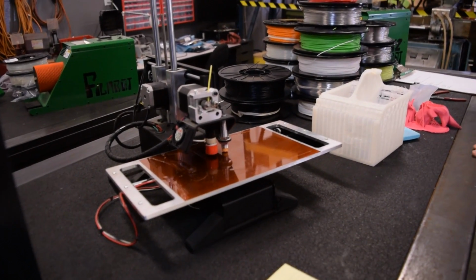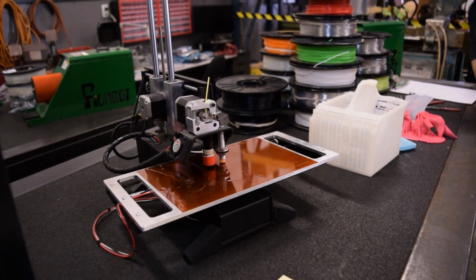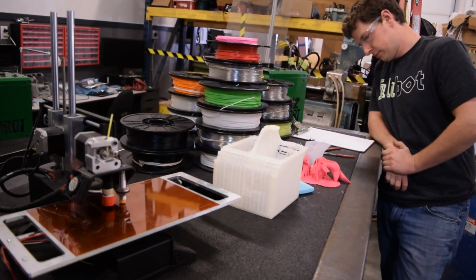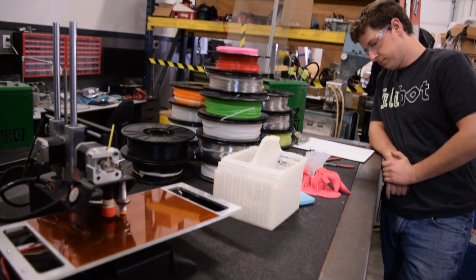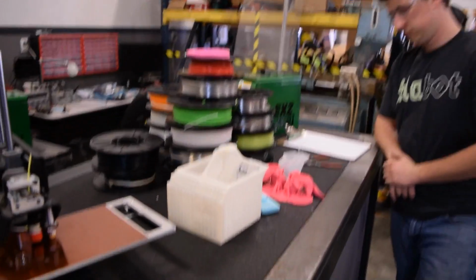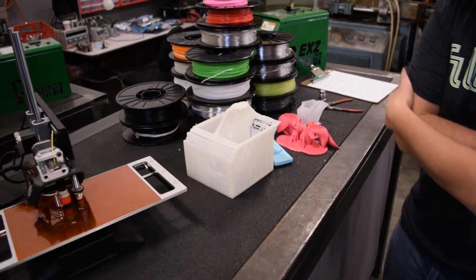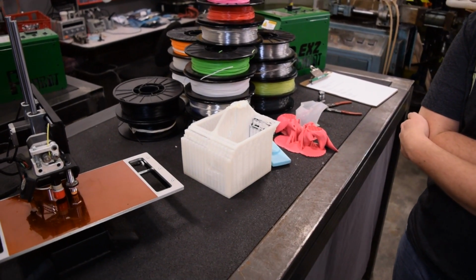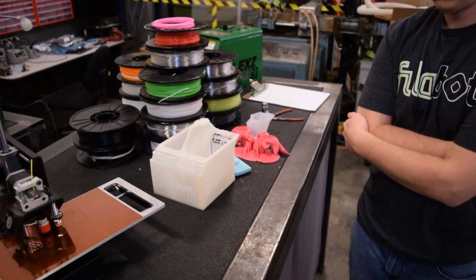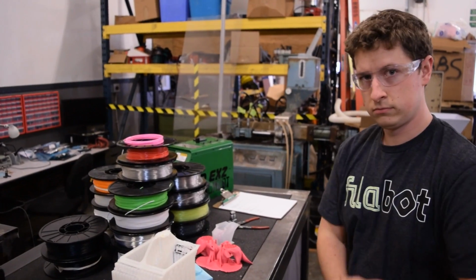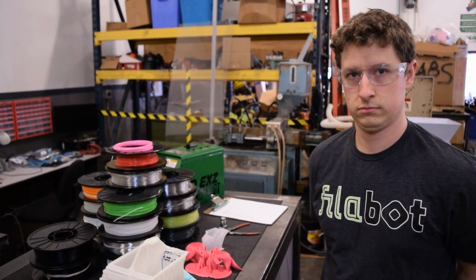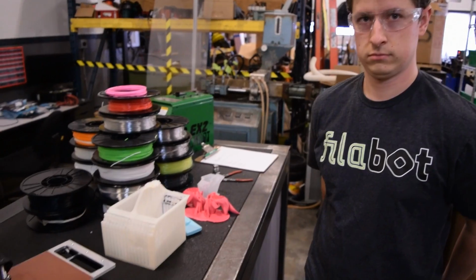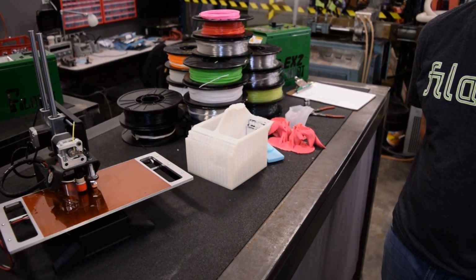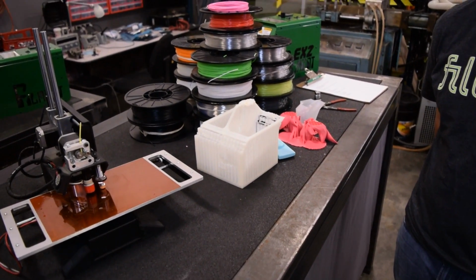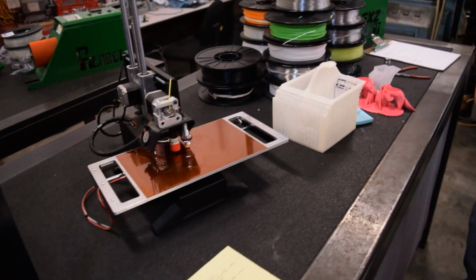So the main point of this video was to talk about how the properties of polymers relate to printer issues. And we went over the warping. That type of information can be found on the data sheets for the polymers. One of the ones that we've had a lot of trouble with is LDPE and HDPE. They have a very, very high shrinkage. They're very difficult to print with because at their melt temp, they expand a lot, and once they cool, they shrink and warp a lot.